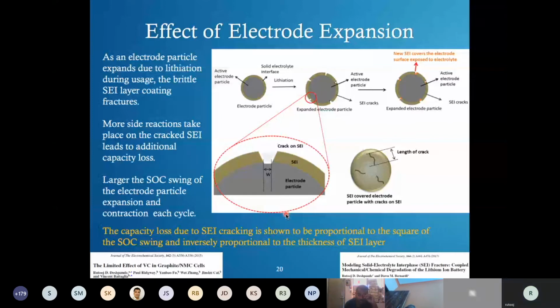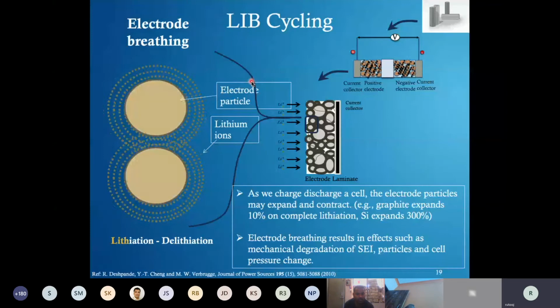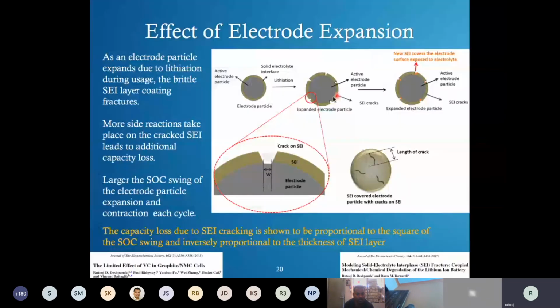Anyway, going back to our electrodes. Remember, our electrodes are surrounded by a coating layer of SEI, solid electrolyte interface. Now, when your electrode particle expands, like what we showed in the previous image, the first thing that will happen is there would be a lot of stress generated on this coating layer. Basically, this coating is not expanding like your inner particle is, and this coating may break.